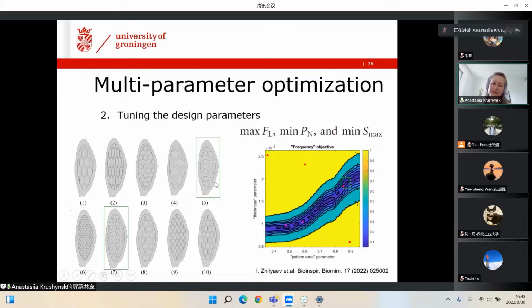These are different designs, but at the same time, they exhibit some similarities. So you can see that the honeycomb is extended along the horizontal direction, so it's quite anisotropic design rather than isotropic, and this anisotropy is beneficial for our target characteristics. So that means that the procedure works, and we can apply it to develop some optimized design. So maybe not optimized in the strict sense, but at least to have controllable flight characteristics.